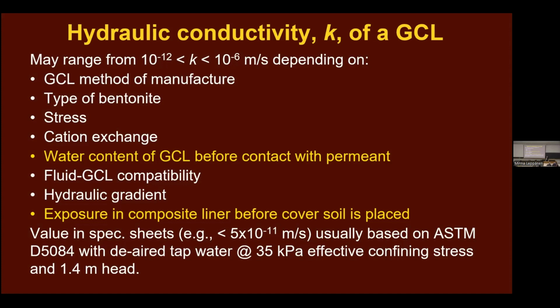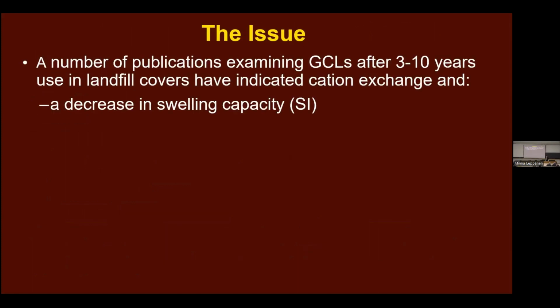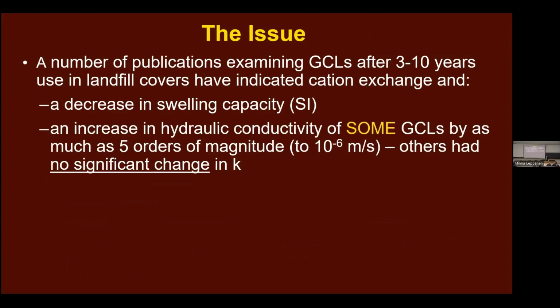You cannot use that as a design value. You need to think about what is the stress and what is the hydrating conditions and what is the permeate that my GCL is going to be subjected to, and select a hydraulic conductivity that's relevant. So there are a number of publications that have shown that over time, particularly in covers, GCLs experience a decrease in swelling capacity, an increase in hydraulic conductivity, in some cases by 5 orders of magnitude, and in others, no significant change at all.